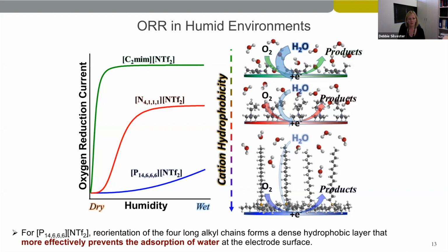And so for the P14666, it's the reorientation of the alkyl chains that forms a very dense hydrophobic layer that effectively blocks water from the electrode. And so this explains why we are seeing our more reversible 1 electron reduction in this ionic liquid, whereas water is now participating in the reaction in the other ionic liquids. So overall, this shows that the structure of the ionic liquid is very important when designing sensors to be used in different humidity environments.